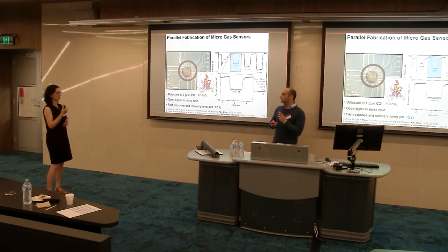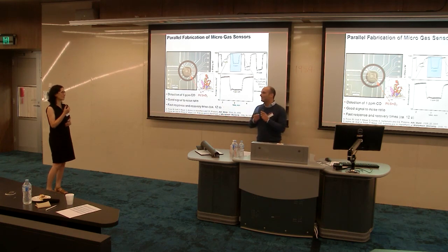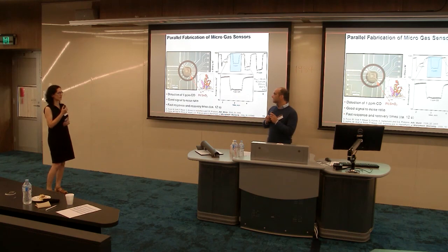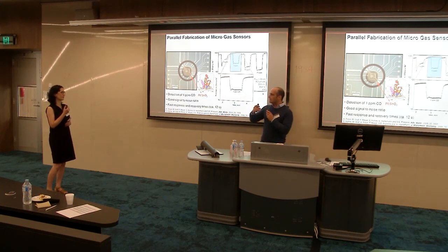It's quite robust if you don't go and touch it. No, but what I'm saying - is it fragile? We have used them over the years in the chambers, and you get quite a robust response. There are other issues, like for example, because it's a high surface area, you tend to absorb contaminants from the atmosphere, and these contaminants may lead to a drift of your response. So it is important sometimes to disturb them - you have to do some high temperature and low temperature cycles. But in terms of mechanical stability, unless you really have a physical interaction, they are stable.